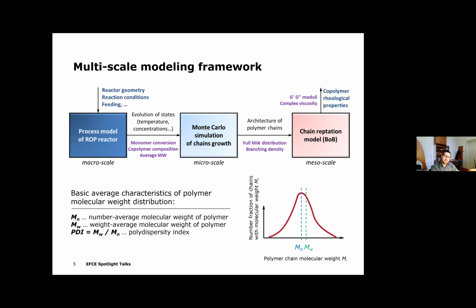Some of the information produced in this model is then sent to the second part, which we call microscopic or Monte Carlo simulation, during which we basically replicate the simulation done in the macro scale, but we look at each chain separately, individually, and therefore this simulation is much more computationally demanding, but it allows us to get detailed information about the molecular chain structure. So using Monte Carlo simulation, we can predict the full molecular weight distribution of the polymer. And then the structure of the chains is sent to the publicly available model called BOB, developed at University of Leeds, which we use to predict the rheological, viscoelastic properties of the polymer melt, mainly the G prime and G double prime moduli as two parts of the viscoelastic behavior.